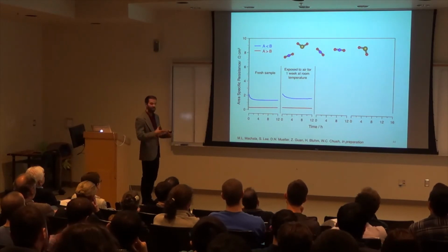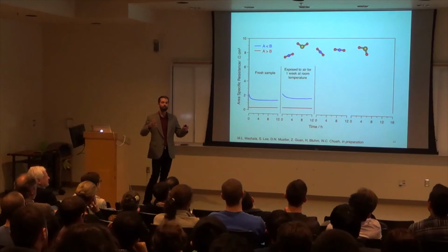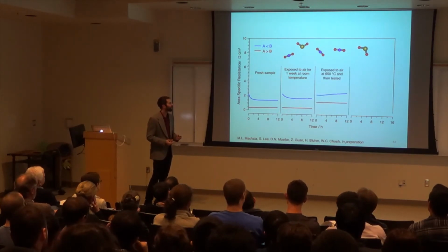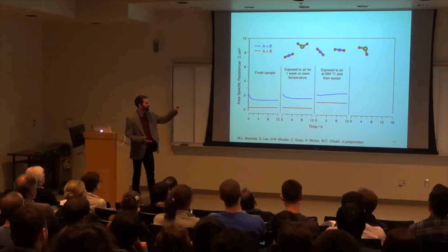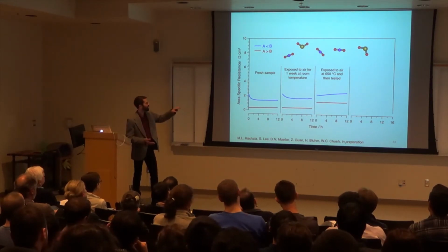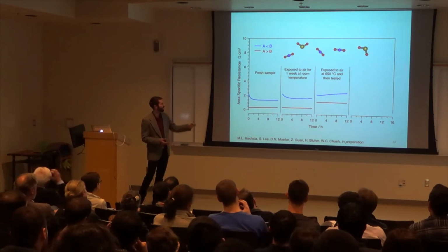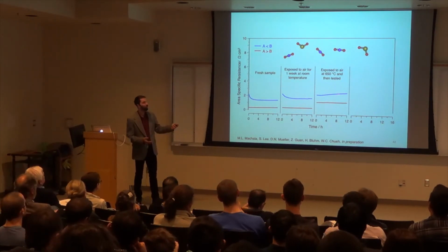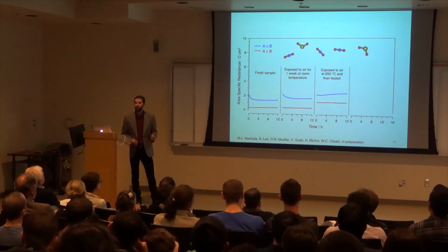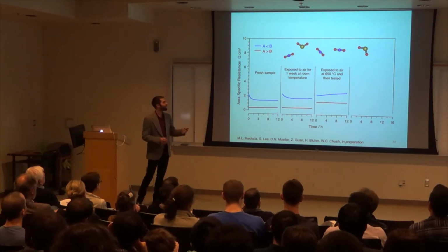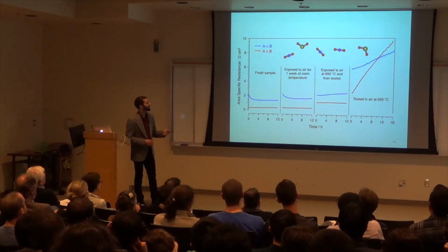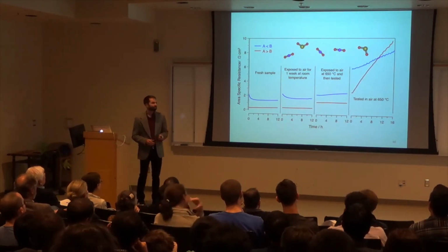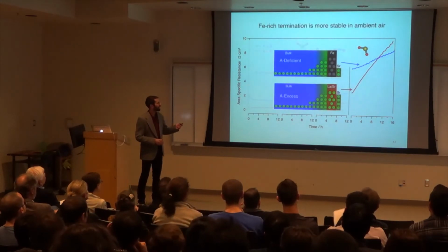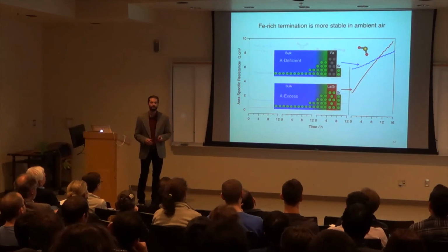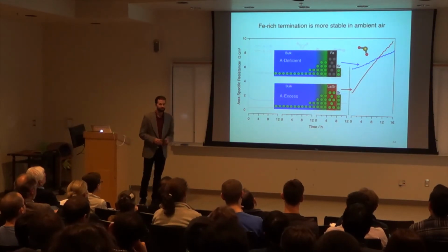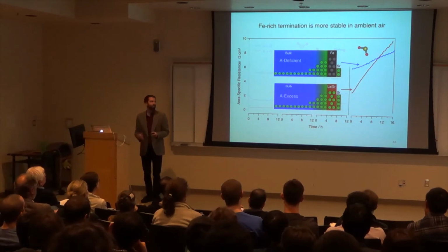Then we decided to take these two samples, heat them up in air, cool them back down, and test them again. We see that they both have about a similar trend. The degradation rate has, they're less catalytically active, but the A-site deficient is still performing worse than the A-site excess. However, when we test these in open atmosphere, we see a different trend. We see that the A-site excess quickly overtakes the A-site deficient. What this tells us is that the surface with a B-site termination is inherently more stable than that of the A-site termination shown here. So now we've defined the surfaces pretty well.